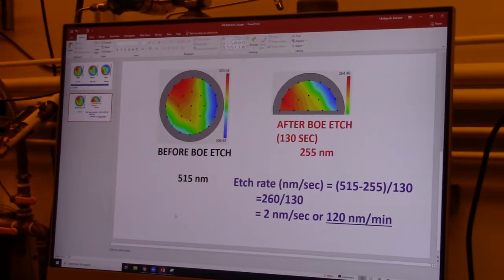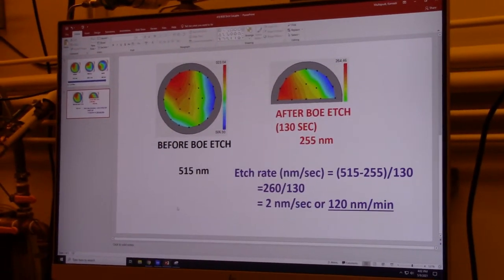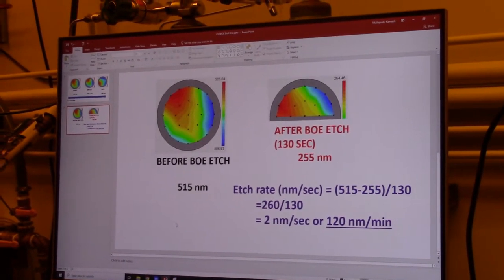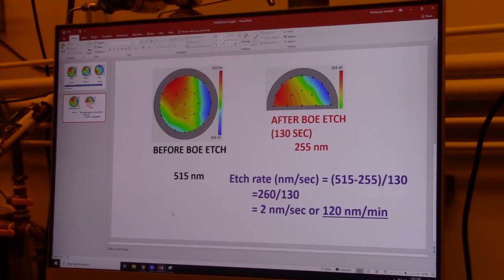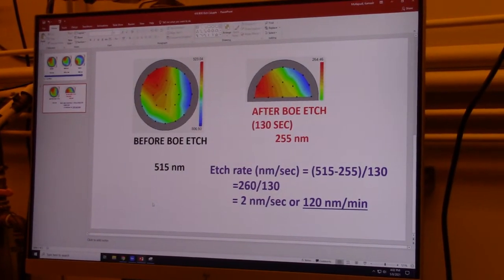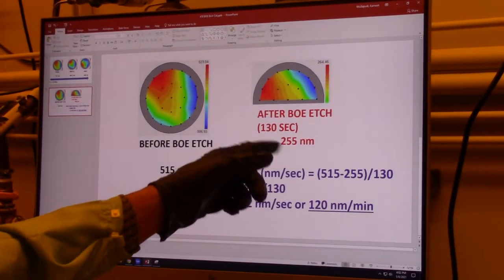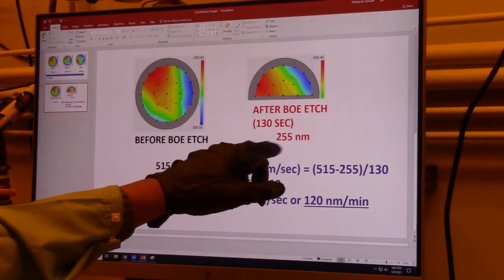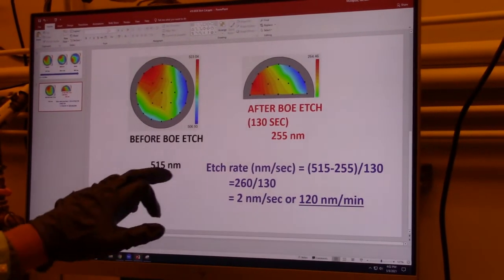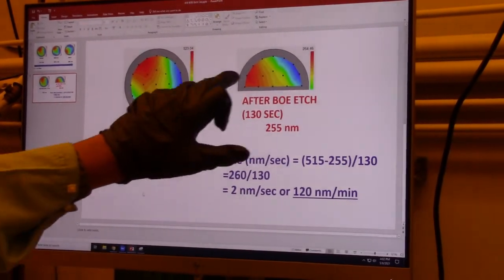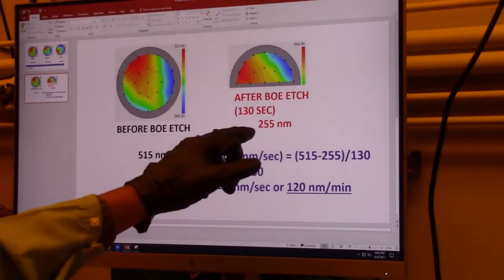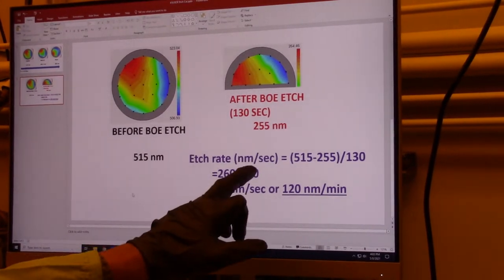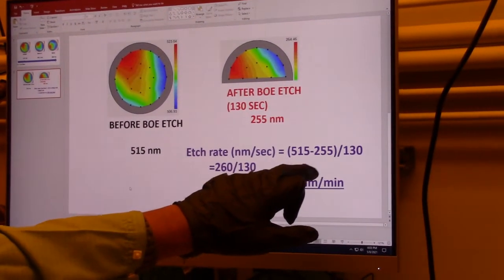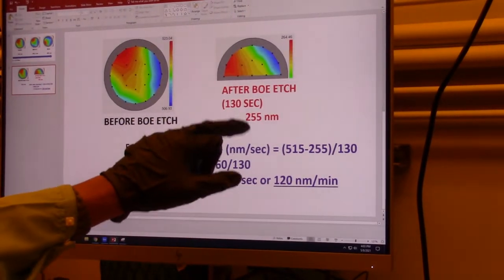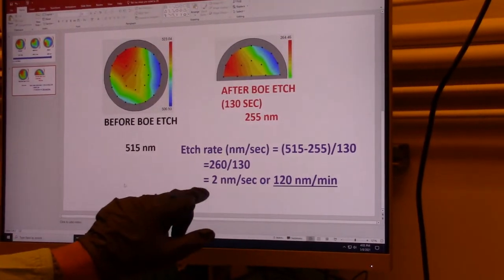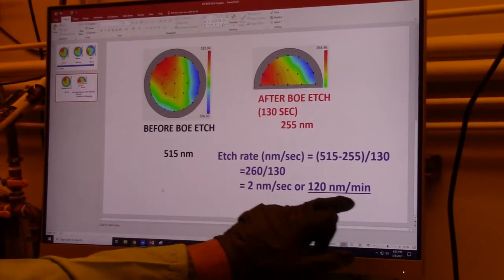As you can see, for the wafer that we diced to calibrate the etch rate before carrying on with our buffered oxide etch, after a 130 seconds, or 2 minutes 10 seconds etch, there's a thickness of around 255 nanometers. So the starting average thickness is around 515 nanometers, and the average thickness after etch is around 255 nanometers. So you can calculate the etch rate as thickness before etch minus thickness after etch by the time, that is 130 seconds. So that's 260 by 130, or 2 nanometers per second, or 120 nanometers per minute.